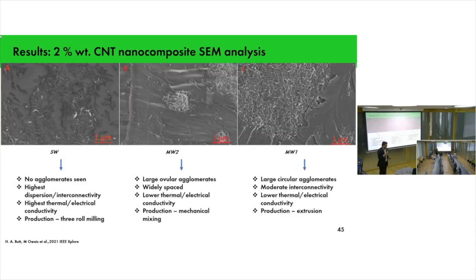So when you see the comparison of all of the 2 weight percent CNT based composite systems, for single wall carbon nanotubes you see there are no agglomerates and there is the highest dispersion and interconnectivity, which helps in augmenting the thermal and electrical conductivity. This was produced by the three-roll milling method. But when you see the multi-wall, you see large agglomerates here, and you see vacant epoxy sites without impregnation. So these agglomerates actually act as pinning centers for the scattering of phonons or heat at this point, which is not good for our system.